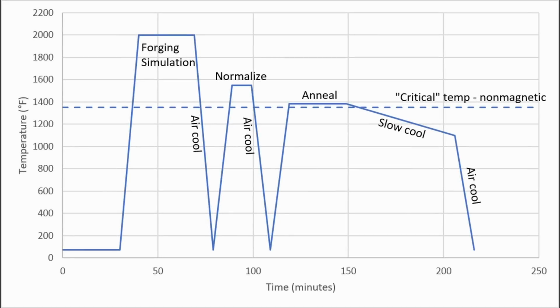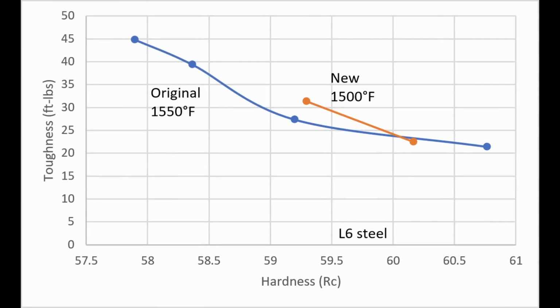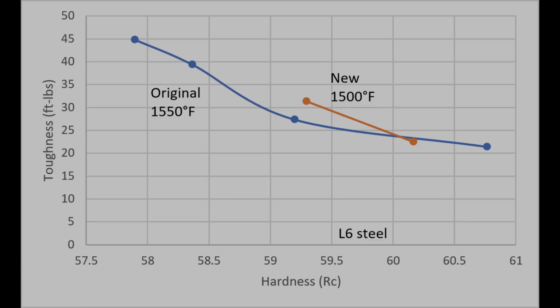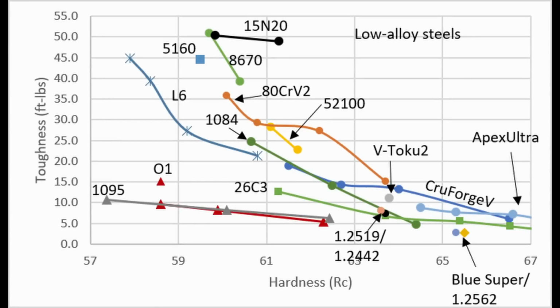I will also do my thermal cycling procedure to see if it's a prior microstructure issue. So I did my same range of thermal cycling with the forging simulation and the normalize and the anneal, and then I austenitized at the somewhat lower temperature of 1500, and ultimately the result was that I got about the same thing as Warren originally got with the 1550 austenitized and the as-received microstructure from the steel company. So why is the L6 less tough than 15N20 and 8670? I still do not know.